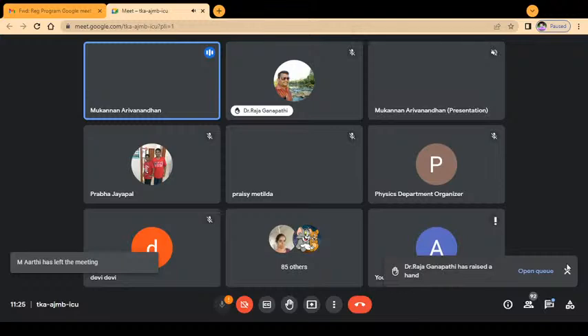The ZT is nothing but S squared sigma by kappa times T, right? So S is the Seebeck coefficient, sigma is the electrical conductivity, and kappa is the thermal conductivity. So S squared sigma by kappa means the figure of merit Z is directly proportional to electrical conductivity and inversely proportional to thermal conductivity. All right? Yes. So if you want to have a high ZT, your material should have high electrical conductivity and poor thermal conductivity.